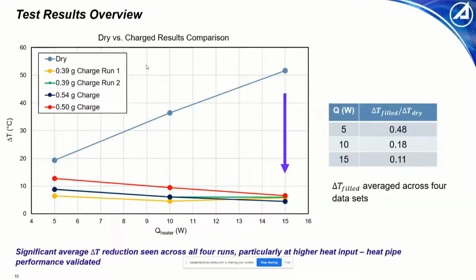The 4 curves at the bottom, there are indeed 4. The green one and the dark purple one overlap, except for in that last 15 watt case, but the 4 curves at the bottom represent 4 filled data sets. These are run with different charge masses that you can see in the legend, consisting of between 0.39 and 0.54 grams. What we did was at each power level, take an average delta T.